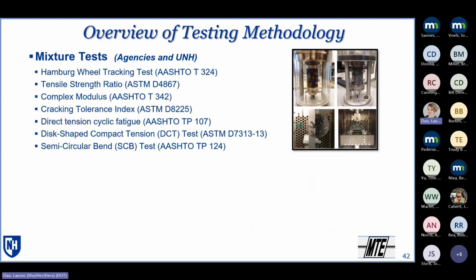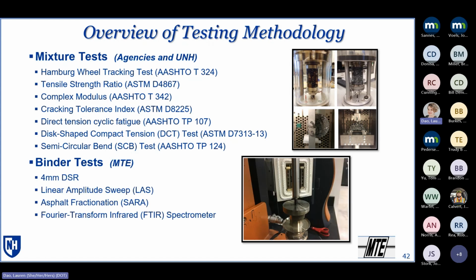So in terms of the testing that was done, these materials had basically the kitchen sink thrown at them. We did almost anything we could that was available at the time, looking at these materials. Some of the testing was done by various NRRA agencies, and a lot of the further testing for the aged materials was done at UNH. You can see a list of the different mixture tests that were completed, and then the binder tests. Most of the binder testing was done by MTE. And again, a lot of different binder tests were done on these materials.